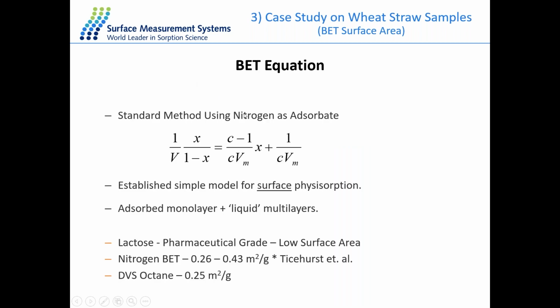So here's the equation of the BET calculation, which is exactly the same as the nitrogen sorption technique, where X is the vapor pressure above the surface, V is the amount of vapor adsorbed on the surface. If we take the left part as the ordinate and plot it against X here, it should give a linear straight line for the regression. And from the slope and the intercept of this line, we can then calculate the monolayer volume, the Vm, and the sorption constant, the C value.